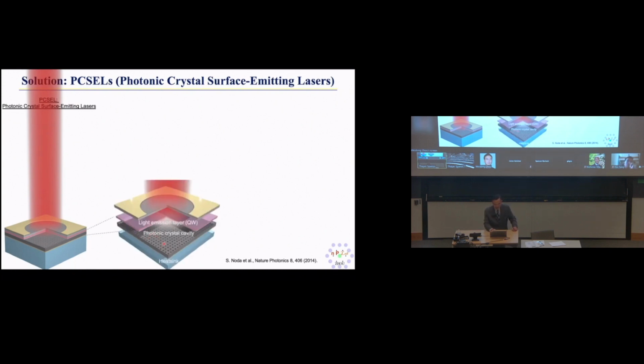It consists of a few layers. One of the key layers here, first start by looking at the photonic crystal layer. I mentioned it's a two-dimensional lattice structure. You can see it has kind of drilled holes, essentially. Literally, drilled holes at nanoscale, made by, for example, using e-beam lithography to form a nanoscale pattern. And we etch using reactive ion etching into the semiconductor material. The structure is in the order of a few hundred nanometer range. So we have to do nanoscale fabrication.